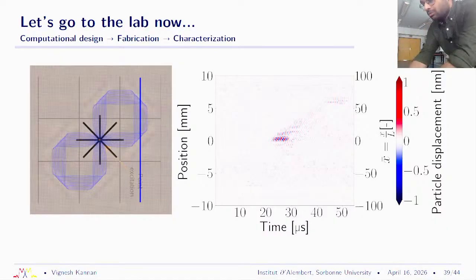We've been asking ourselves the same question. One thing we know is that the wave speed is anisotropic. So the wave speed in this direction is different from the wave speed in this direction. So it's possible we weren't collecting enough data at long enough times to see the arrival of that second wave, because that might have been slower. So that's the only hypothesis we have right now, but we're still trying to figure it out.